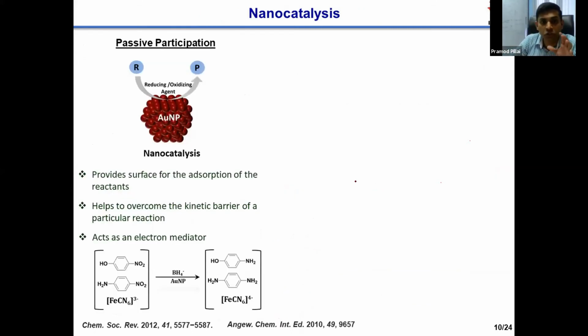There are generally two model reactions that people work on in nanocatalysis to prove their hypothesis. One is passive participation, where the nanoparticle is not directly involved in catalysis; rather, it provides its surface for the adsorption of reactants, and it helps in the mediation of electron transfer between the reactants. In this case, you need an additional reducing agent like sodium borohydride. One of the classical reactions here is the nitrophenol reduction to aminophenol in the presence of borohydride.